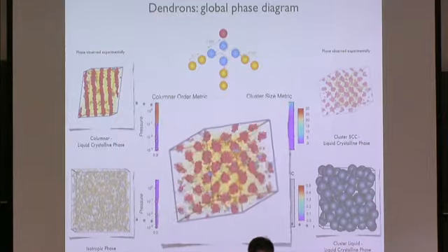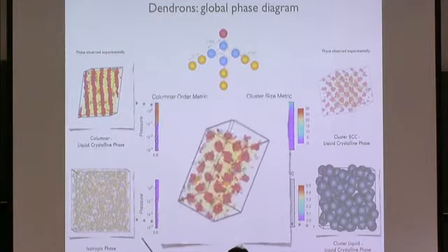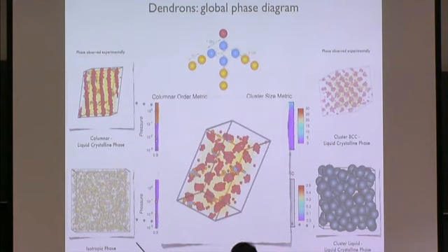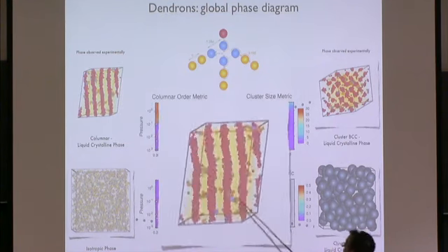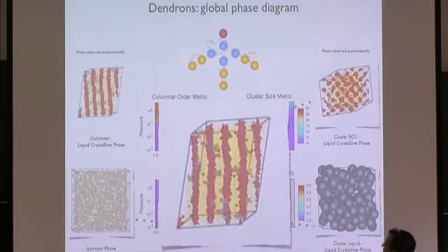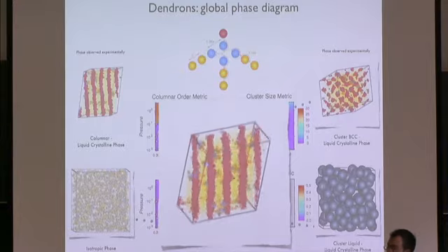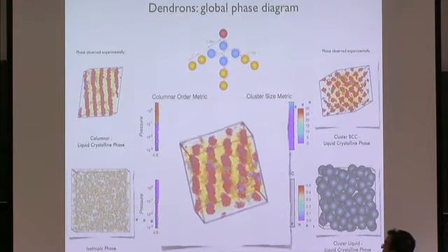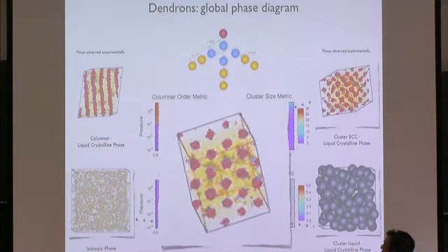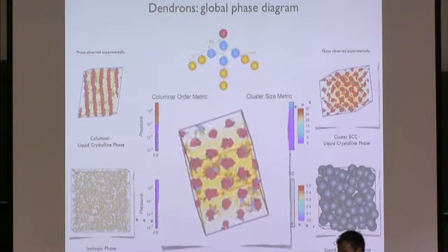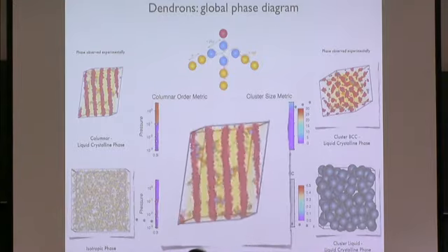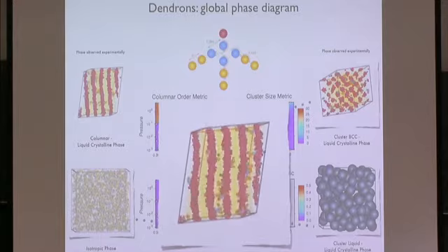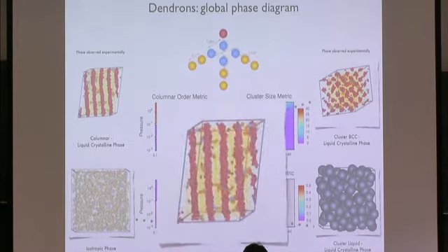Keep lowering the temperature or increasing the pressure, and what you see is that these spheres now coalesce into a columnar phase, which is again reminiscent of what the pizza wedge model showed. So we see that we can see all of these phases without the need of any artificial description of effects of sizes and things like that.